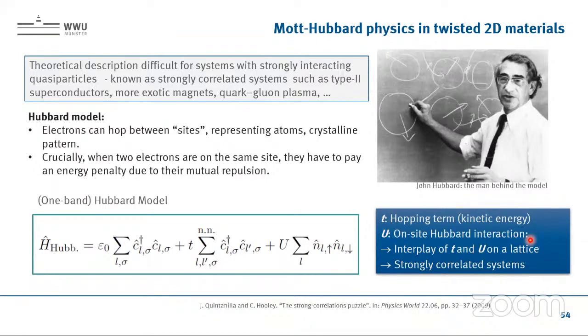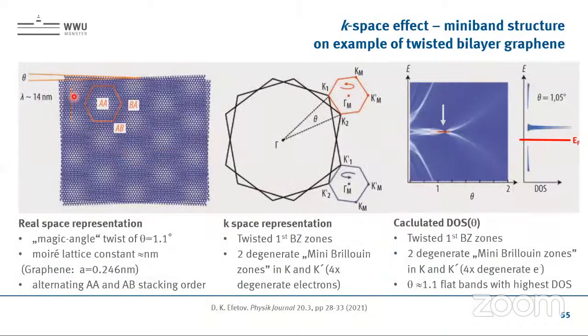And now, this is a theoretical concept, but it's hard to prove it experimentally. And now with this twist degree of freedom, it can be proven, because now we have exactly those lattice sites. And then you can play with the Fermi energy to say, well, we have just every second site filled. And if every second site is filled and every other second site is half filled, it already means that they have some attractive potential, because this site would like to have another state. This one has one. With that, it's like an exciton, like an electron-hole pair, which can bind. And with that, you can drive these phase transitions if then the interaction between different sites is strong enough.